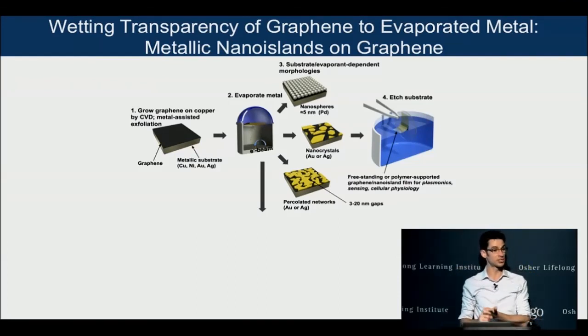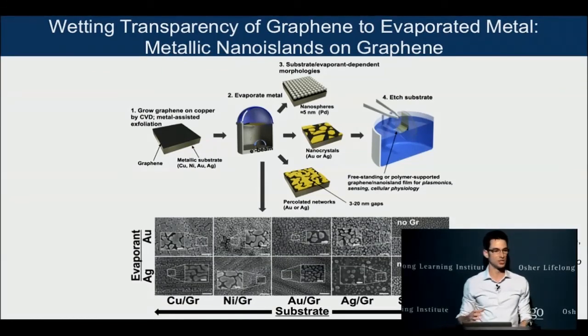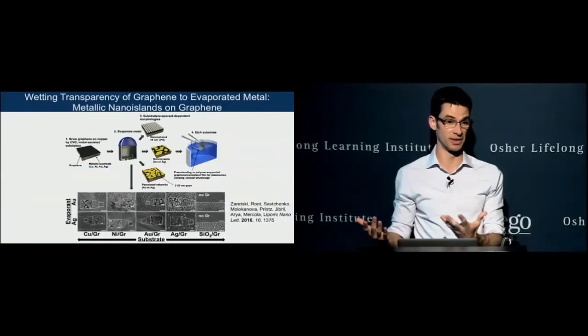It's called wetting transparency. And what we did is we found out that this works not only for water droplets, but also for thin films of metal. So we can make this zoo of metallic nanoparticles that are very closely spaced. By nanoparticle, I mean characteristic dimensions of a billionth of a meter.